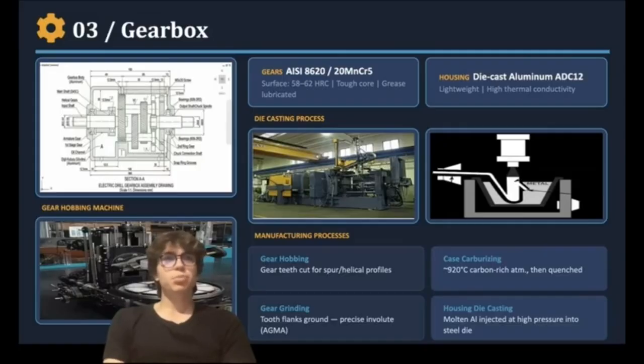The manufacturing process starts with gear hobbing, where the gear teeth are cut using a hobbing machine for spur and helical profiles, as you can see in the photo of the gear hobbing machine. This is followed by case carburizing, where the gears are heated to approximately 920 degrees Celsius in a carbon-rich atmosphere and then quenched to achieve the required surface hardness. The tooth flanks are then ground to produce a precise involute profile meeting AGMA quality standards.